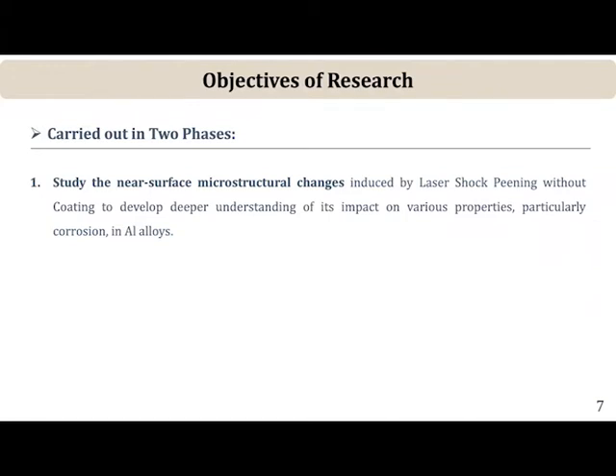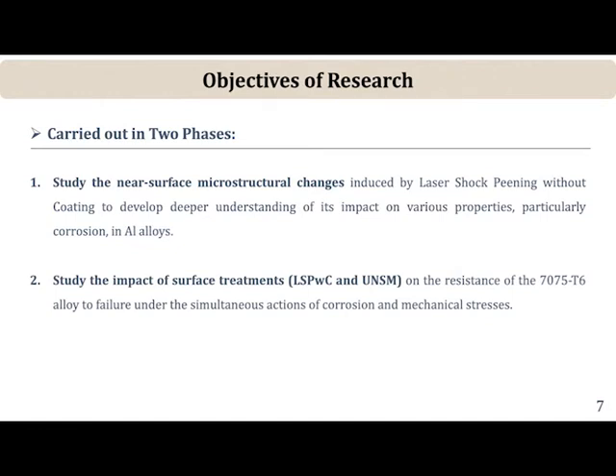He first looked into detail at how laser peening and the other technique of ultrasonic nanocrystal surface modification bring about microstructural changes, what impact that has on properties, and whether one can achieve some kind of mechanistic understanding of not just the impact of compressive residual stresses, but more importantly, and this is something the earlier speaker alluded to, that these surface treatments are not just about introducing compressive residual stresses. There are significant near surface microstructural changes and gradient microstructures that are produced, which are less understood and which also have a huge impact on the fatigue life.